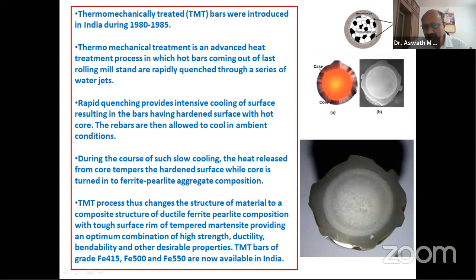This is the actual sample I have taken from a factory. After this proper quenching system, you get rings like this. In general terms, people in the field use this as a ring test. So you have to conduct a ring test on a reinforcement bar. If you get three rings like this, the core, then the transition layer, and then the outer hardened surface, then it is a good quality TMT bar, properly manufactured.